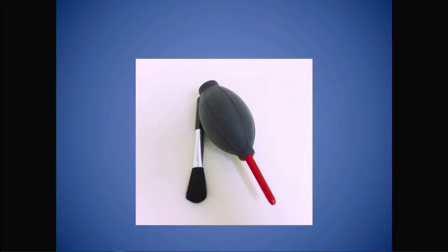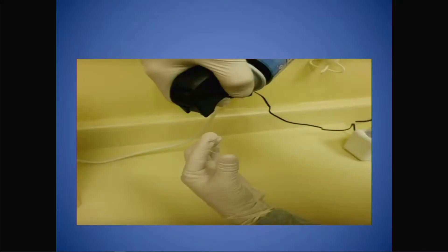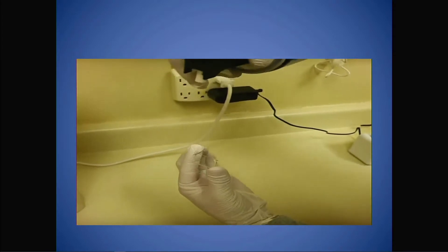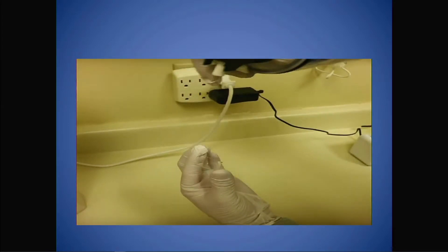The first step is always debriding the surface, and I would recommend using a soft brush or one of these air bulbs, which you can buy at camera stores. Now, people use canned air, and that is not a good idea. There are lots of additives in the propellant which you don't want evaporating onto the optical surface. Also, if you don't hold the can perfectly vertical, a full can sometimes spews out the propellant itself. Here's a little video demonstrating that. See, that's propellant actually leaking out of the can — that happens when you hold it more horizontal. If you hold it more vertical, there's less chance of that happening.